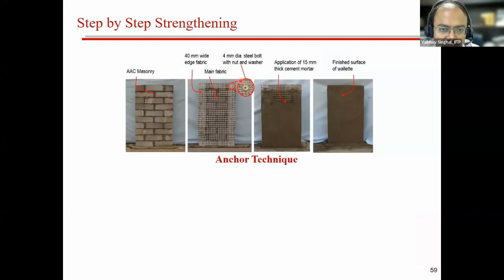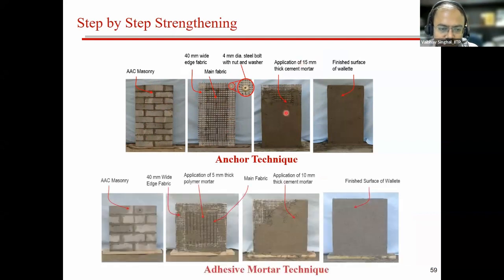So this is called the anchor technique. You can see this is a plain surface of a masonry. We first applied the main fabric. Over the main fabric, we have this edge fabric, and then these are the anchors. The anchors are simple anchors. You can use a simple nut washer assembly also as an anchor. And then we directly applied a thick layer of mortar, 15 mm.